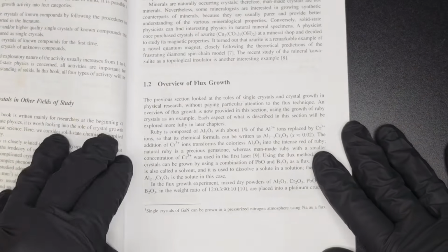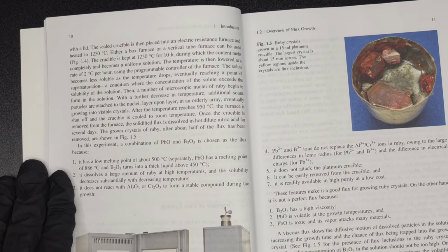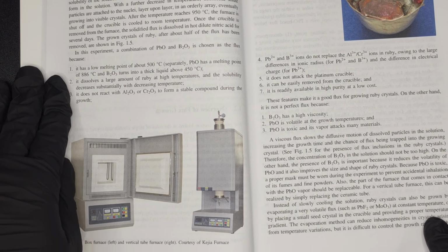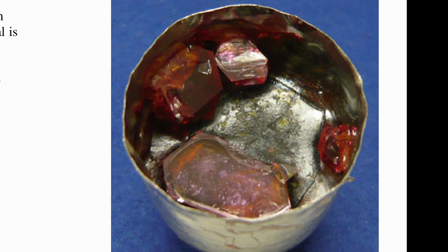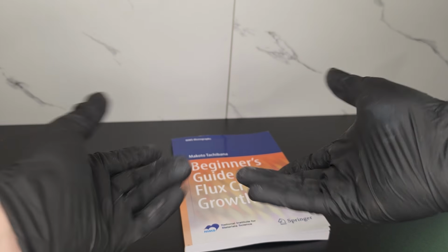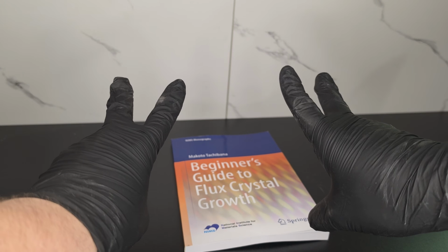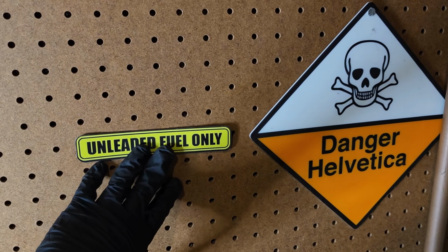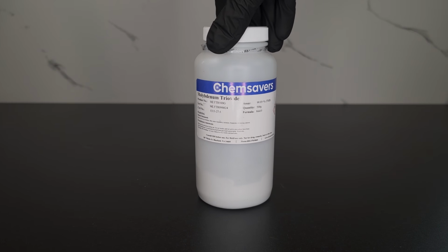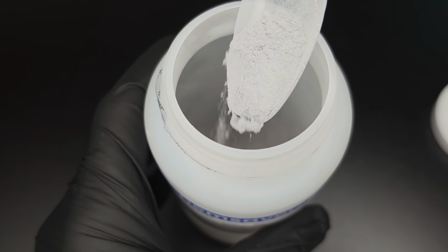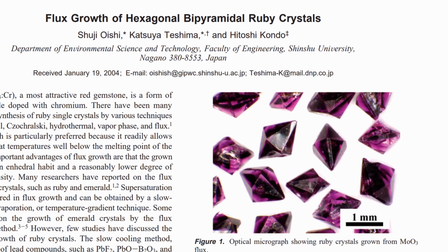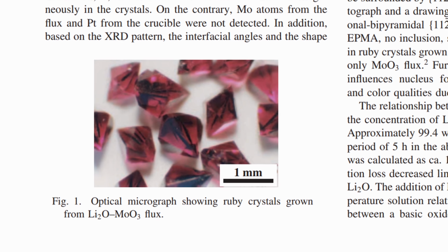So I cracked open a book and I quickly found a very easy way to do it. Using a mixture of lead oxide and boric acid in a platinum crucible, you can grow big rubies in a week. But there are a couple problems with this. First, I want this project to be super fun, not super fund, so I'm not going to fumigate my garage with lead. The best alternative is molybdenum oxide, which is much safer but tends to evaporate out really quickly. These papers only showed off very small rubies, but I just hoped I could improve on that.